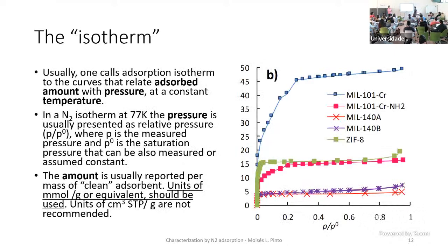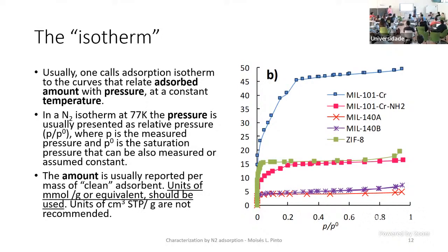Okay. So, this is the isotherm that we normally use for characterizing the material. This is the adsorption isotherm of nitrogen at 77 Kelvin, so it's at the temperature of liquid nitrogen. And before performing these experiments, just to have this completely clear, we usually call this the adsorption isotherm, and we have in this case the relative pressure here, and here again the adsorbed amount, and this needs to be at constant temperature. This is why we call it isotherm.